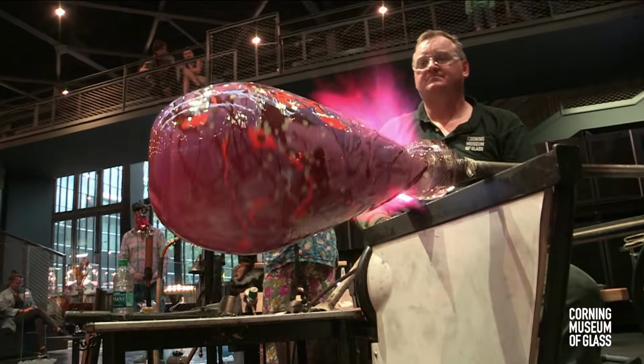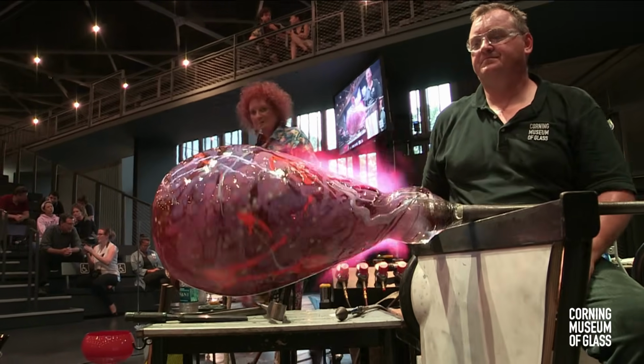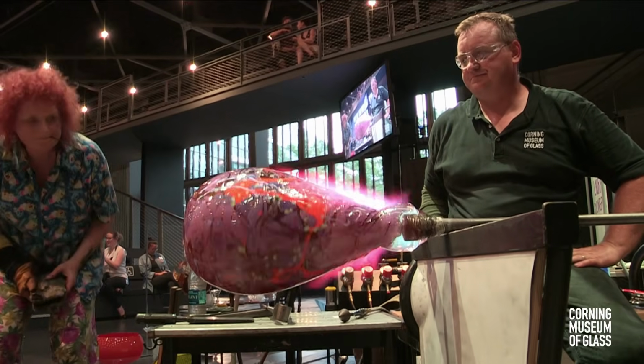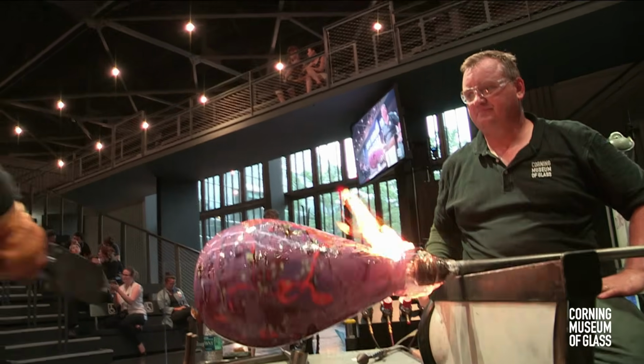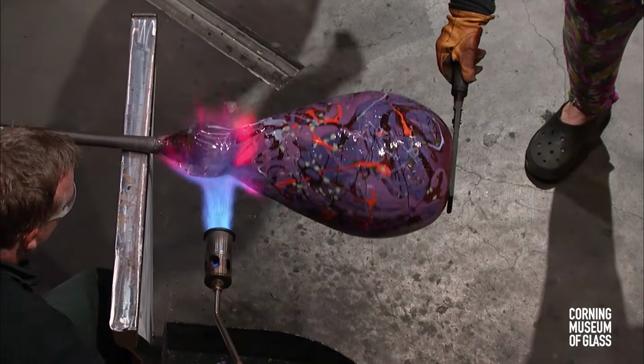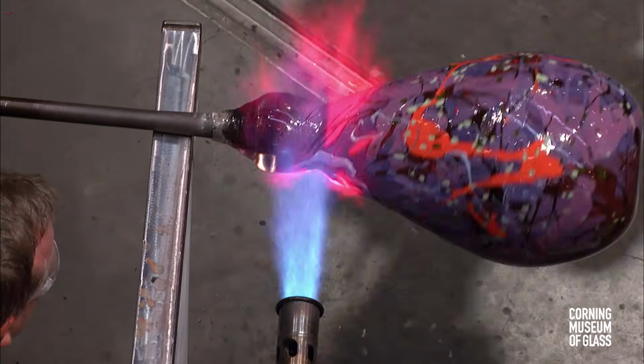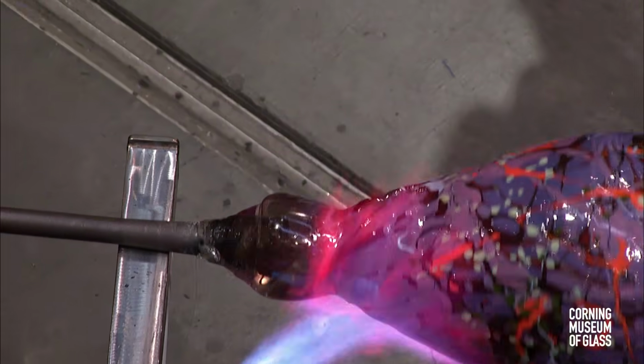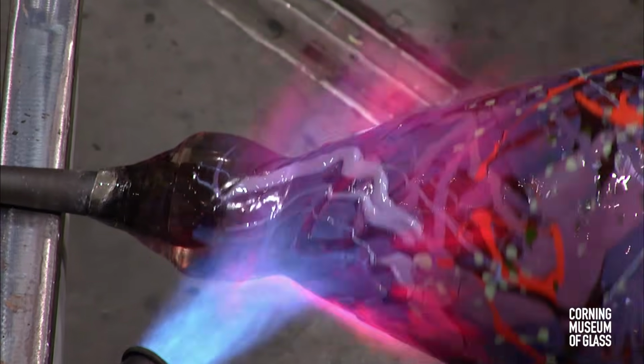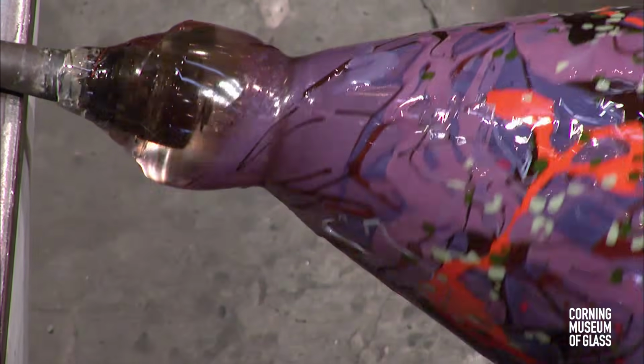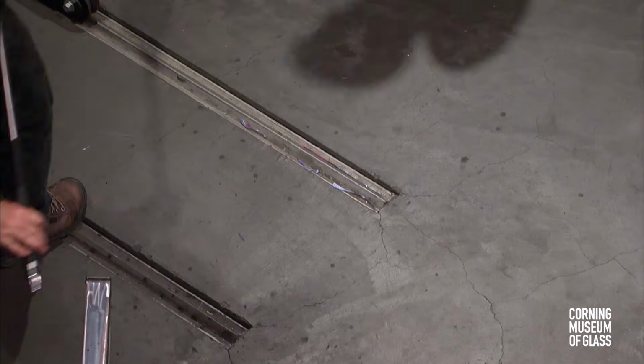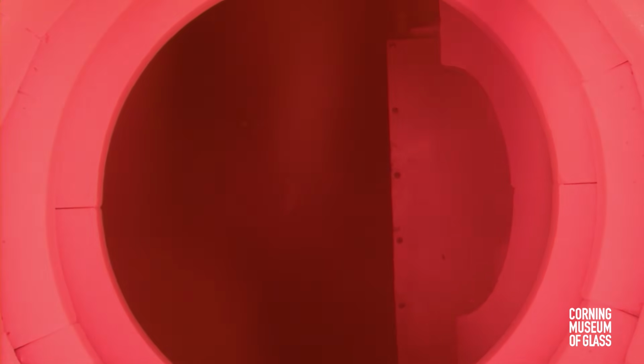Probably the most critical of that sense of timing is in this transfer that we're about to do. They need to make sure that the piece is warm enough to not crack, but cold enough to actually crack at the top edge. They need to make sure that the punty that Jeff is working on is hot enough to stick to the bottom gently, but if it's too hot, they won't be able to control it. Then they might have to wait for the punty to cool down, which would make the top a little too cold. If it's too cold in general, then the whole thing can be too cold and separate early.